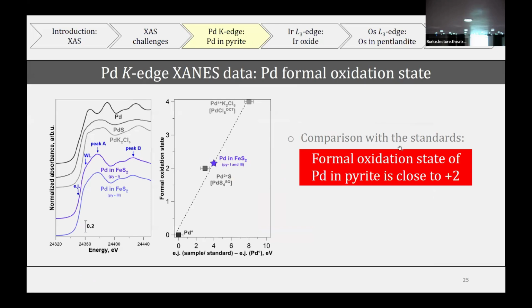Then we performed the XAS experiment. These are some standards containing palladium and our samples, which look almost identical, and we plotted the formal oxidation state as a function of the edge jump of the sample or standard minus metallic palladium. Comparison with the standards for this calibration curve shows that the formal oxidation state of palladium in pyrite is close to +2, which is quite logical because the iron formal oxidation state in pyrite is close to +2.